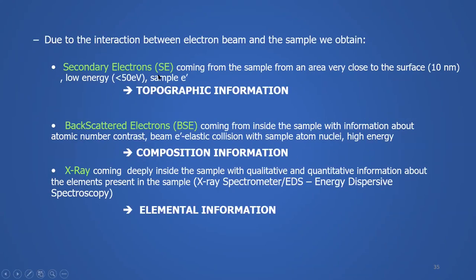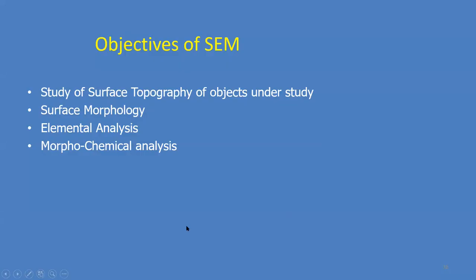So for the three types of signals, from secondary electrons you get topographic information. This is important, right? These come from an area very close to the surface, typically about 10 nanometer depth of the sample, and these are low energy electrons. Then you have backscattered electrons, which give composition information. These come from inside the sample, and these are higher energy electrons. And the third kind is X-ray, which gives you elemental information.